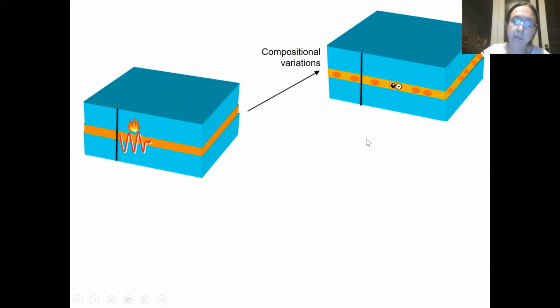And what we've said already is that the indium content of indium gallium nitride controls its band gap. So the indium nitride has a really low band gap, gallium nitride has a really high band gap, so that the bits with lots of indium in will have a low band gap. They are the low energy place to put my electron and hole. So my electron and hole are going to sit in these, what I've got drawn as dark orange regions, these high indium content regions, and be trapped. There are barriers, changes in energy, which prevent them from getting to the defect. So they'll recombine and give out light.